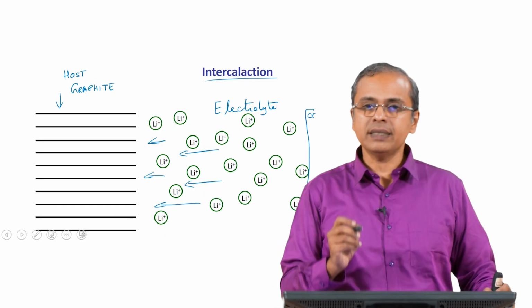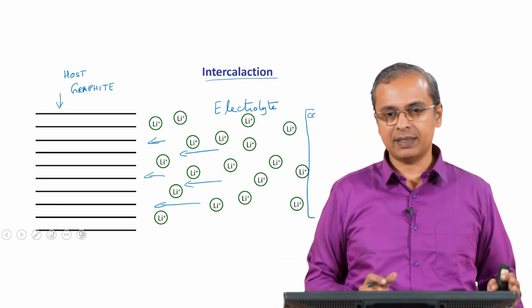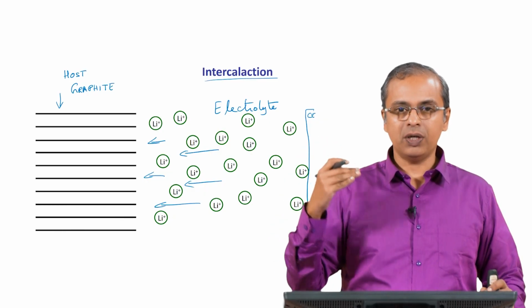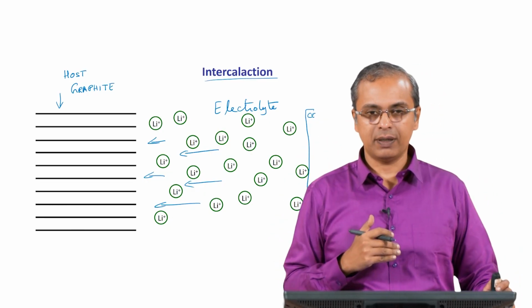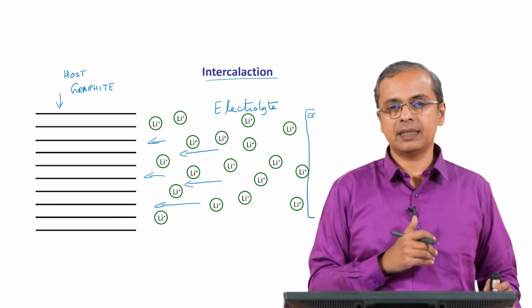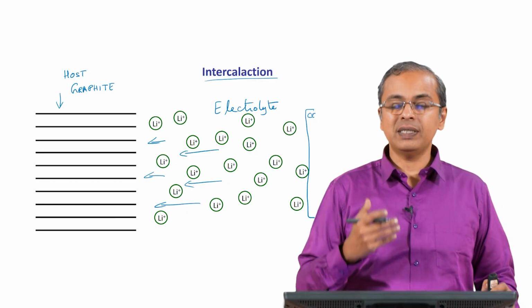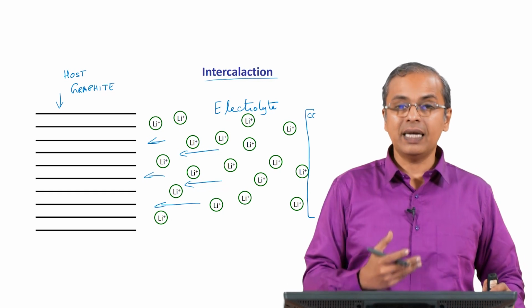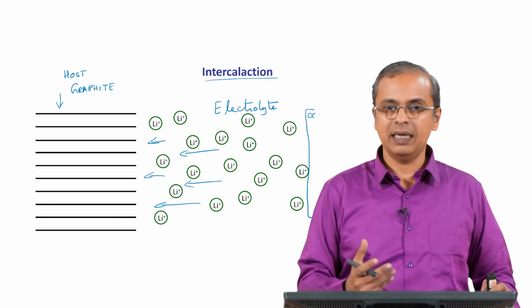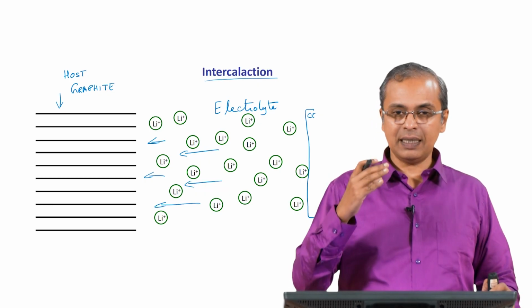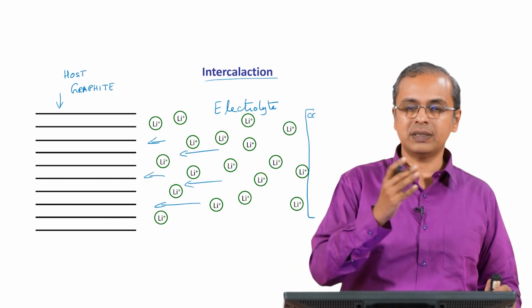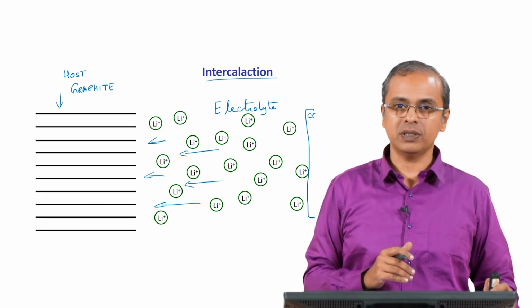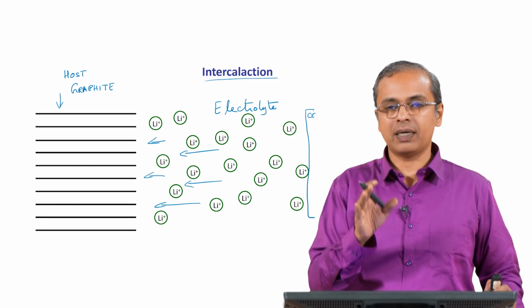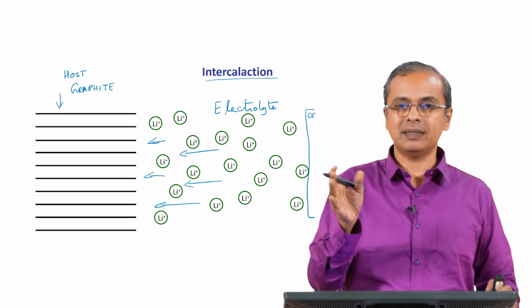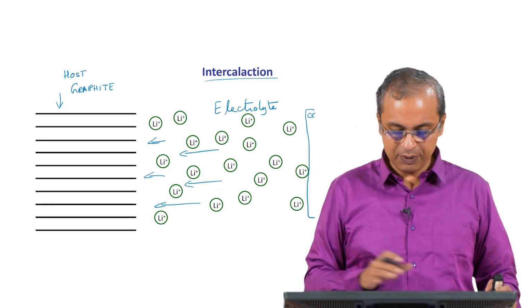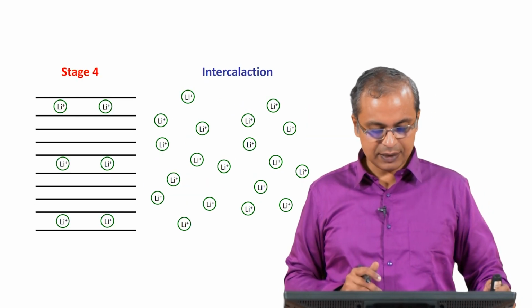Okay. So interestingly what happens is they do not just randomly enter this graphite structure, they do so in some kind of a periodic manner. One very periodic, systematic manner in which they enter this graphite structure has been noticed, and that is referred to as staging. Lithium enters graphite in stages, and that process is referred to as staging. And what happens is there is a stage 4, stage 3, stage 2 and stage 1 kind of situation that arises in this process. And when you reach stage 1 only, you have reached the complete completion of the reaction, and you have LiC6 at that point.